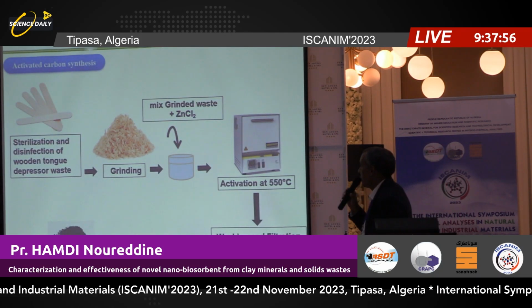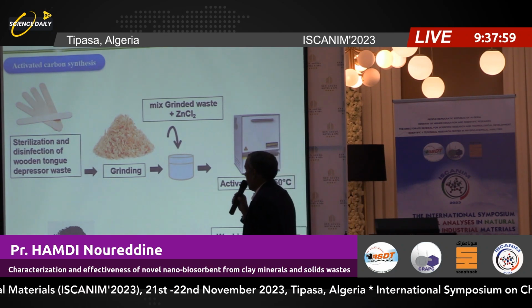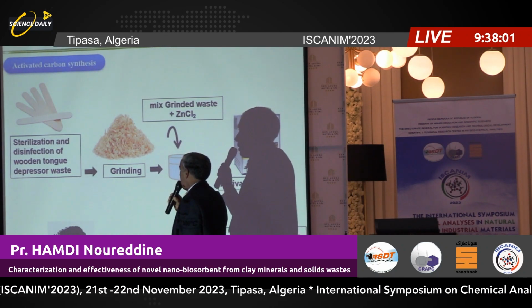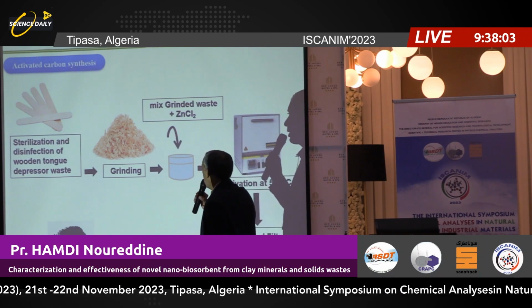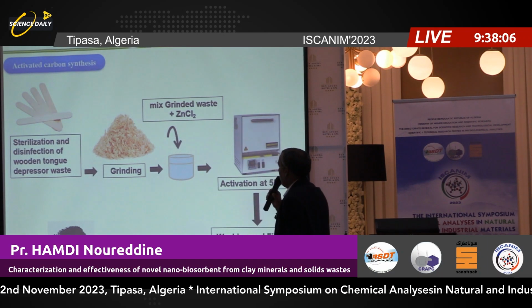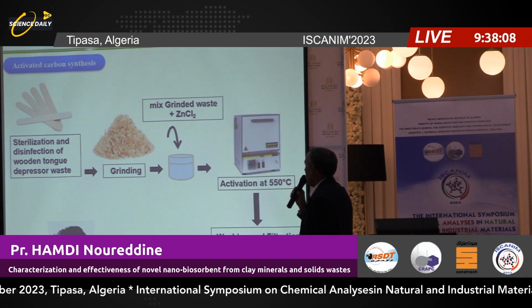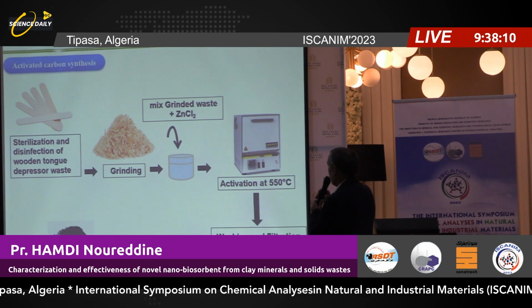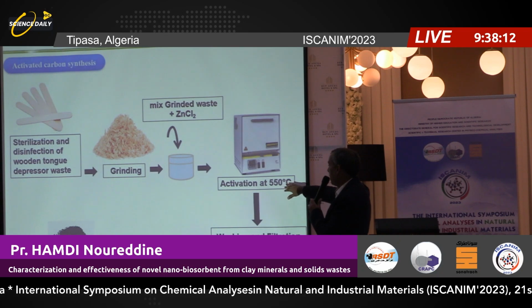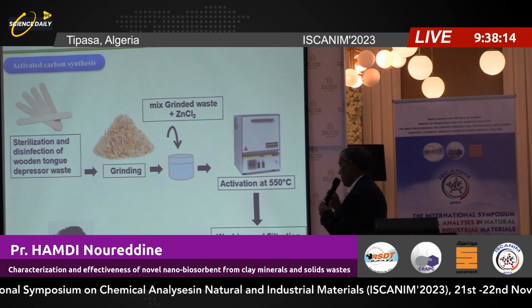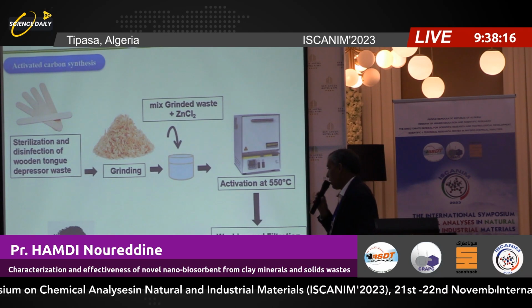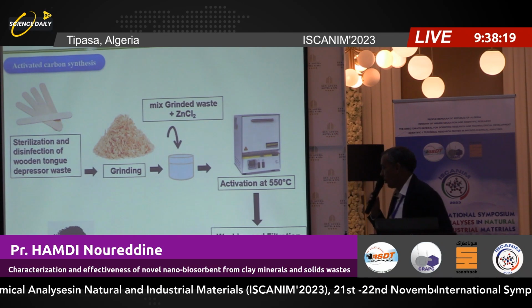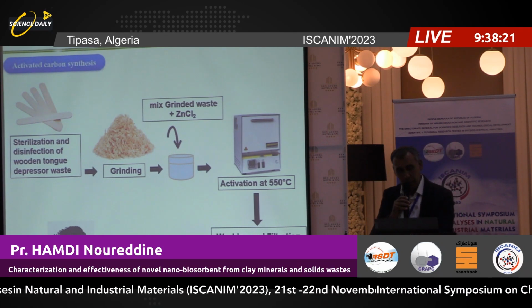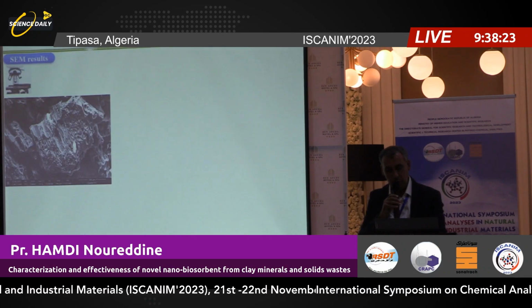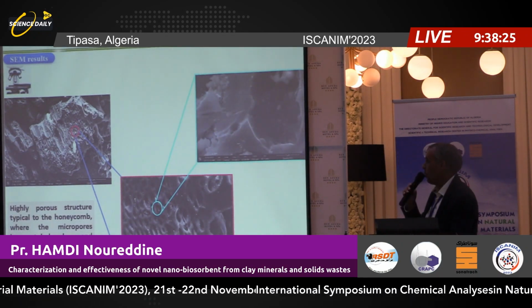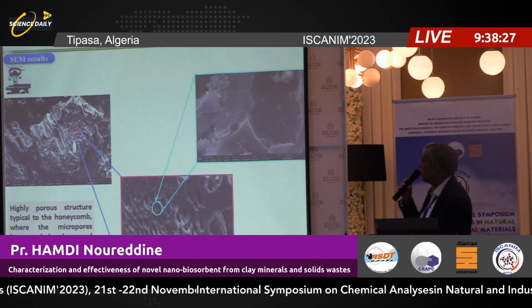Now the preparation of activated carbon using the waste of the wooden tongue depressor. Firstly, grinding the waste. After that, adding the zinc chloride and activating at a temperature of 550 degrees C, washed and filtered, and after that dried at 80 degrees C for 12 hours in order to obtain the activated carbon. The characterization by scanning electron microscope